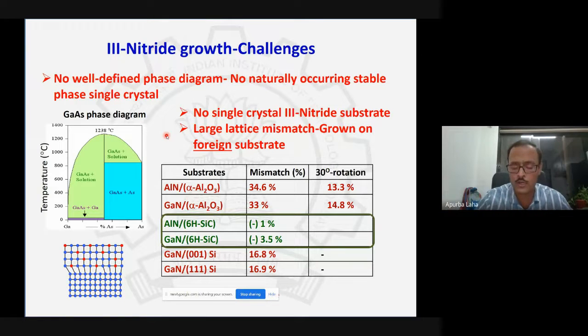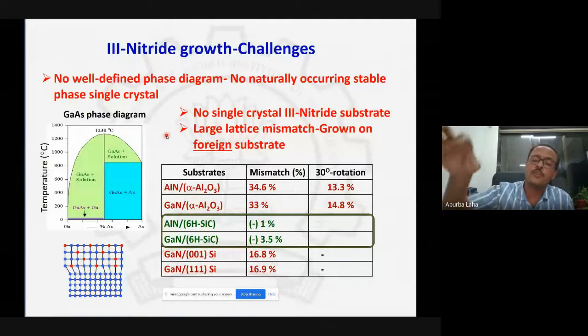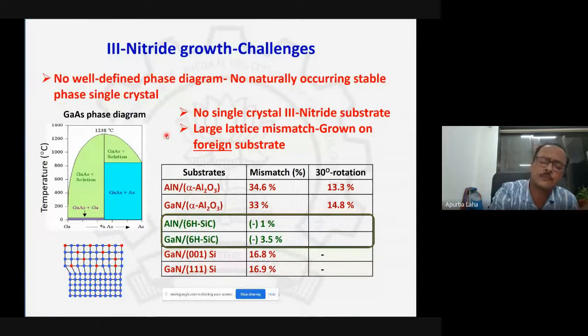Let's talk about the water system, for example. 0 degree is the temperature where three phases exist. Now, if you bring the temperature down a little, let's say minus 0.05, then the stable phase is the solid phase. It solidifies, because the temperature gradient is the driving force for the thermodynamic transformation of the liquid phase to the solid phase. And typically, this is what happens in single crystal formation.